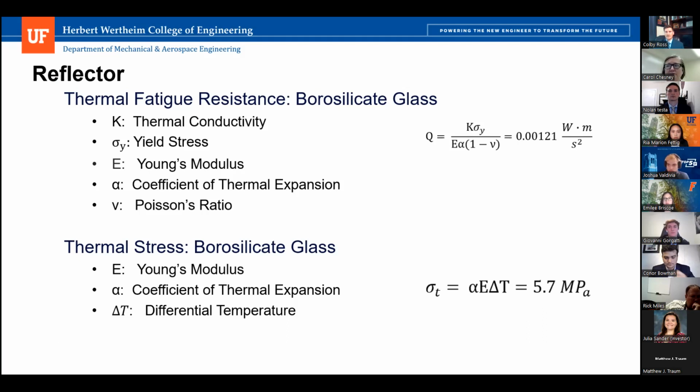We found that the soda lime glass that's commonly used does deteriorate over time because of thermal fatigue: expanding, contracting, cold temperatures, hot temperatures. It breaks down the aluminum coating and potentially the silicone holding everything in place. So that's why we went with that. No, that's good. I appreciate the explanation.